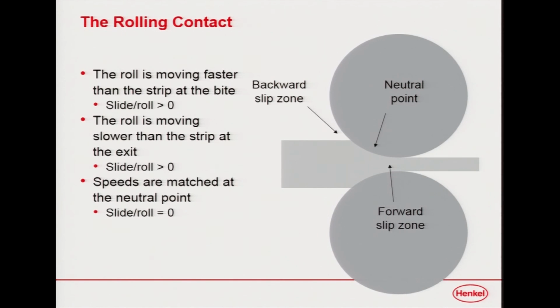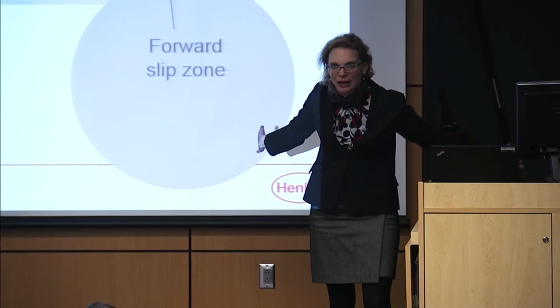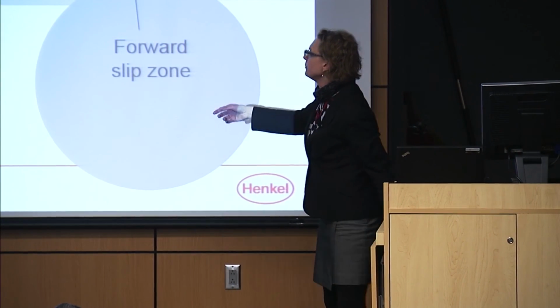We have something we call the neutral point, which is where the strip is moving at the same speed as the working roll. The working roll is the thing that's applying the pressure and squishing the steel down. We have what we call the backward slip zone, where the steel is moving slower than the roll, and the forward slip zone, where the steel is moving faster than the roll. Try to come up with a more challenging contact mechanically. I dare you. This is about as bad as it gets.